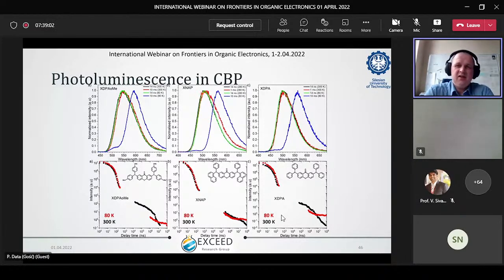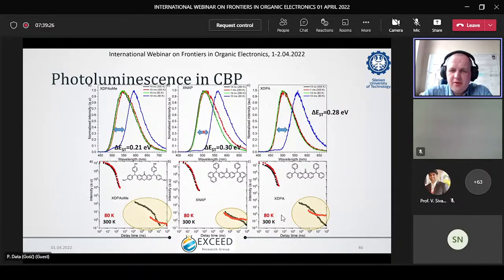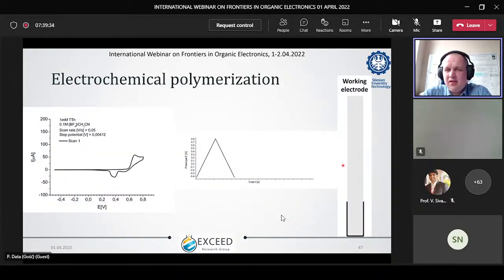So very nice matrix used for OLEDs, and we checked how they behave. Like we expected, our ST gap dropped, so we know that it will be more efficient for OLEDs to use CBP. Nevertheless, the gap is still high, and we want to drop this a little bit further. We want to have a lower ST gap and a higher delayed fluorescence contribution. What to do? Again, use electrochemical polymerization.